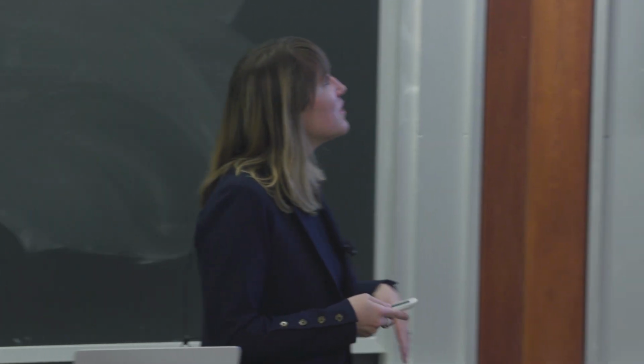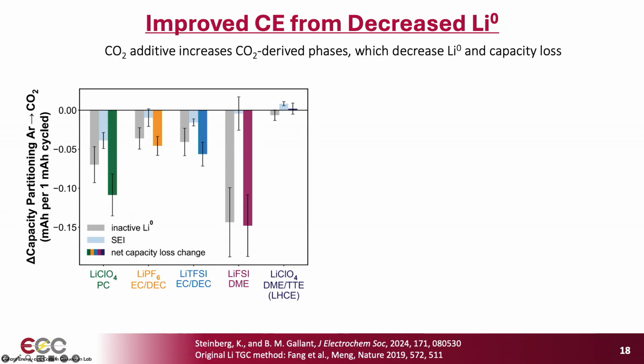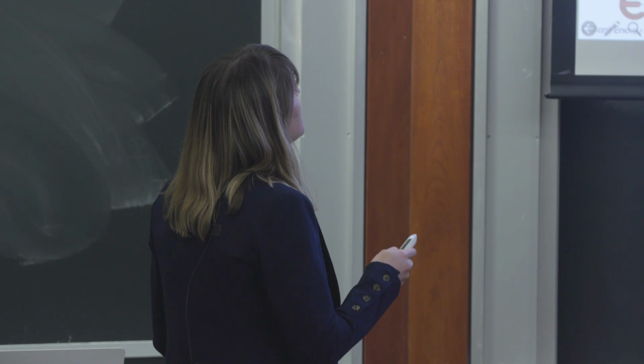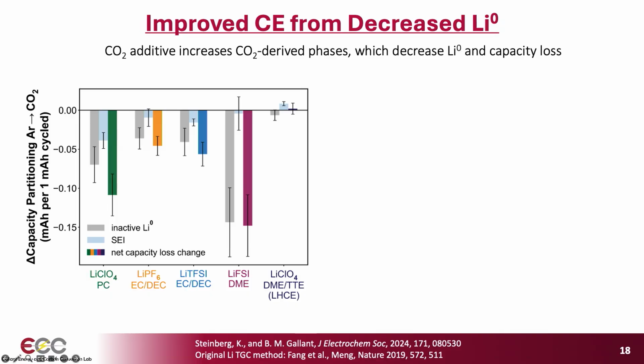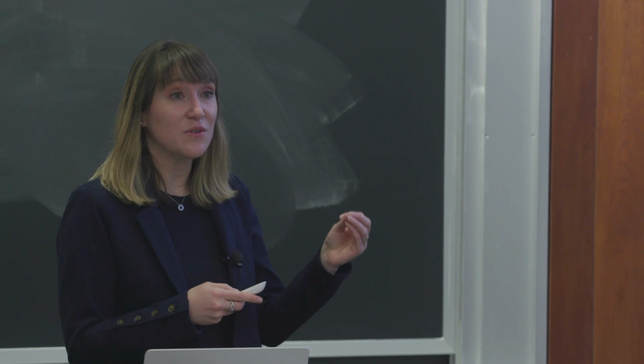That's fine, but now we actually have the tools to be able to tell us why. So using titrations, we dug into that question. This graph shows the change in capacity loss, moving from the cells with argon to those with CO2. Anything below the x-axis here that's negative means that the capacity loss decreased when you have CO2 present. In other words, the Coulombic efficiency increased. So the solid bar, for example, in this electrolyte here is the total capacity loss change. And then to the left, we can see whether that's attributable to SEI in blue or inactive lithium zero in gray. And in the 4 cases where we saw an improvement, the improvement was largely, in fact, overwhelmingly, due to a decrease in dead lithium in the sample.